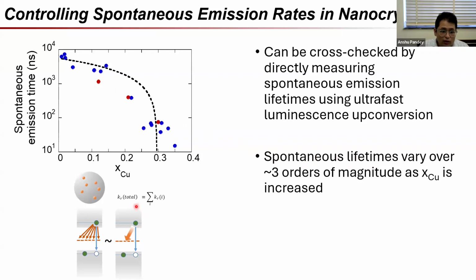So long story short, what really is copper doing? Well, something like this. Each of these copper atoms in fact presents a new path. So the electron which sits in the conduction band wants desperately to fall back into the valence band. And it can do this normally just like this. But what each of the coppers does is that it gives it an alternate path through which to fall through. And because of that, the net rate which we measure is in fact a sum of all these rates. This leads to a very fast emission lifetime, which is again unprecedented. It's a very simple trick, a very simple idea of kinetics being played out where we are not seeing any interference or anything else between paths, but rather just a straightforward sum, which is leading to these observations.